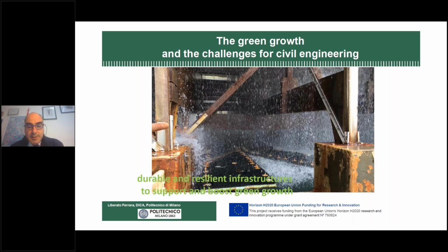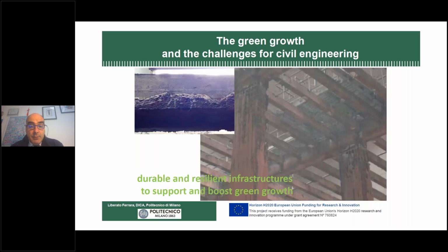This is a cooling tower structure. So you see this water is rich in sulfates, is rich in chlorides, and there is the abrasion due to the rain. This is the service condition for 364 days per year. The structure rests only 1 day per year for the maintenance. And this can be the consequence of corrosion of the concrete, of the matrix, due to the sulfates.